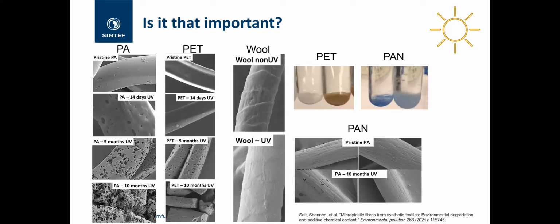And without going into detail, on the top right, you can see that UV exposure changes the PET, the polyester, from a white to a sort of brown color. So it's evidence of oxidation. And if we look back at the PET under the scanning electron microscopy images, you can see that we go from the top of the column over 14 days down to 10 months. And what we're seeing is quite strong changes in the surface properties, and they become very, very brittle as well. So we get a lot of fragmentation.